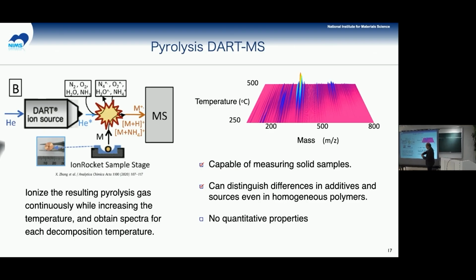To increase the number of data, we use pyrolyzers. In that case, we put the samples here, only several micrograms of the samples, and then heat it to pyrolyze these samples. Then only the gas phase, the fragmented molecules, can be detected by the mass spectroscopy. By changing the temperature of these heaters, we can obtain the heat map data at once. Within only 15 minutes, we can obtain the big data of the mass spectroscopy. Each temperature has its mass spectrum, from room temperature to 600 degrees Celsius. So by sweeping the temperatures we can obtain many data at once.